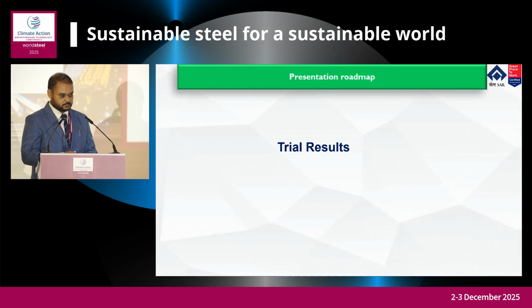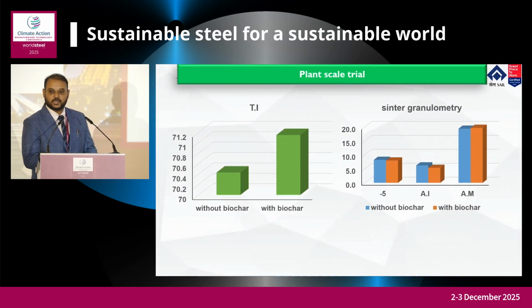And the trial results, these are industrial trial results. We can show that the tumbler index and the Sinter granulometry have both benefited from these biochar additions because of its higher temperature generation and low flame front generation. The tumbler index, AI and AM: AM is the short form of arithmetic mean size, which is a requirement of the blast furnace for very good blast furnace operation and reducing instability. And AI is a measurement of Sinter superfines generation, which is also an emission criterion. We had to maintain a lower AI for a better environment.